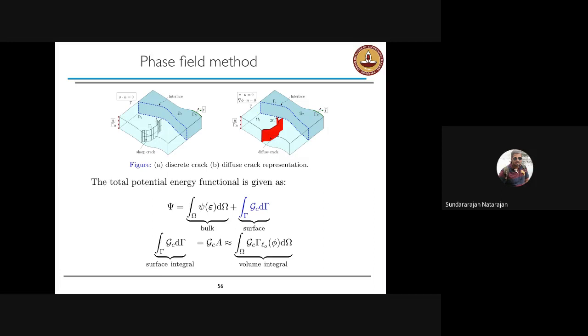One is the bulk and the surface, because every time the crack is evolved or formed, there is a new surface that is formed. And for the crack to grow, there has to be an energy that is spent to form this new surface. So this is the basic idea of Griffith, and that's how fracture mechanics came forward.